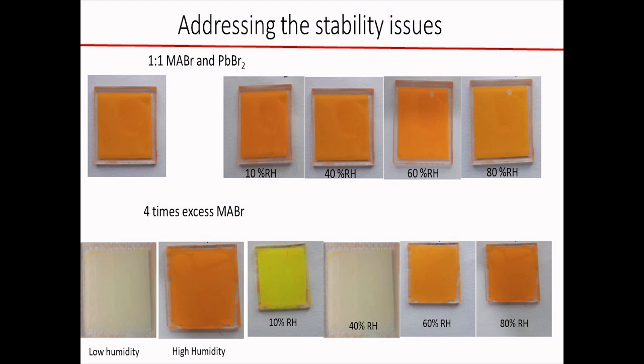So we have done a systematic study by actually taking 4 times excess methyl ammonium bromide and also a 1:1 ratio. The 1:1 ratio film doesn't really change much at 10% or 60% RH, but if we keep it at 80% RH, the film has slightly degraded.